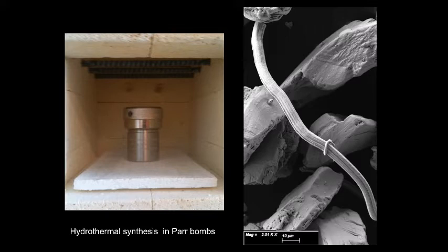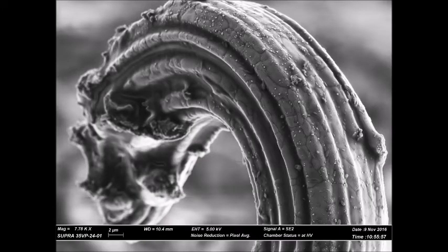And this is an SEM image of an example of a wire that has been grown hydrothermally in the laboratory. Now, based on all of the experiments that we've done, hydrothermal, in the flame, and in the scanning electron microscope, and analysis of the resulting samples, we have a model and a much better understanding for how these wire silvers are growing. First of all, the texture of the wire silver, which previously had not been fully understood, is comprised of multiple small single crystals over which the striations are superimposed.